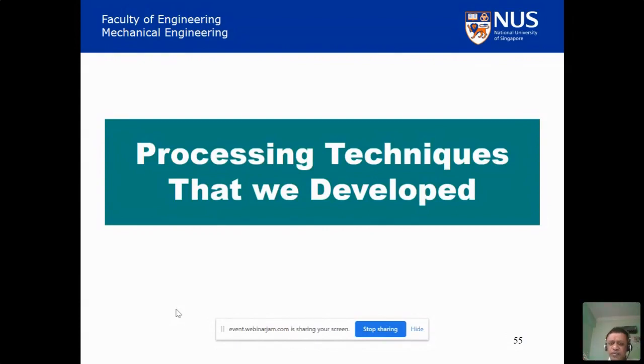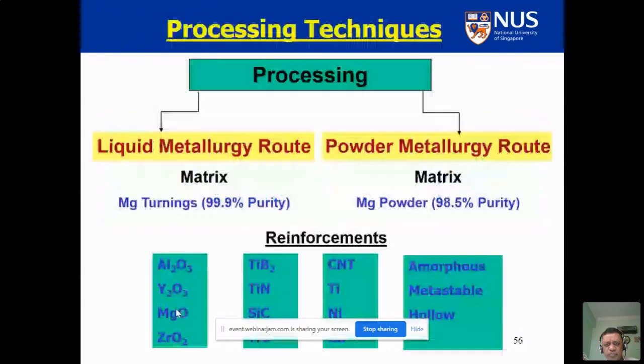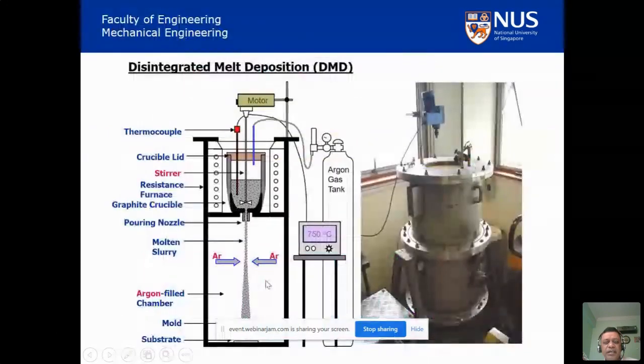So in the last 20 years, we developed two techniques which are quite unique to us to make both aluminum and magnesium-based materials. So the current emphasis is on magnesium. You can make any metals using two methods: the liquid metallurgy method or the powder metallurgy method. And in the composite, you can put the reinforcement to improve the mechanical response of the material. So this is called the disintegrated melt deposition technique, which we pioneered in 1995 using the concepts of stir casting and spray atomization and deposition.